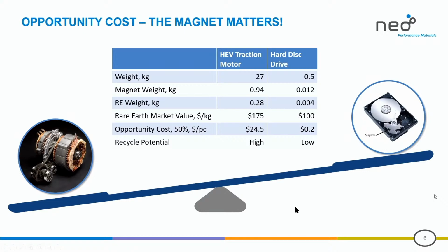And the iron has no value, and so only the rare earth in the magnet has value, and the rare earth is typically about 1/3 of the overall magnet weight, so the actual weight gets reduced. And so now if you take the rare earth market value of the magnet in a traction motor, because it uses heavy rare earths for temperature resistance, the rare earth value is around $175 per kilo. But the rare earth value in a hard drive is only about 100, and that's at today's prices. A year ago, those numbers would have been half. So the market price of rare earths is important as well.